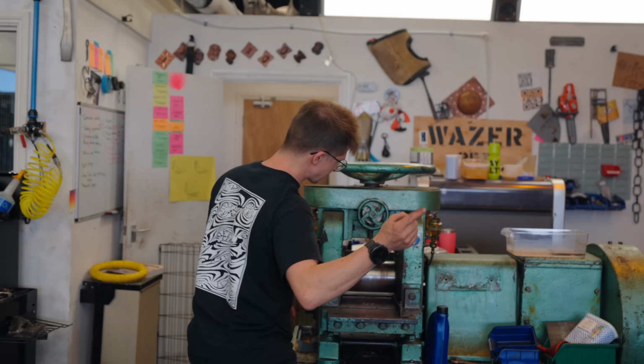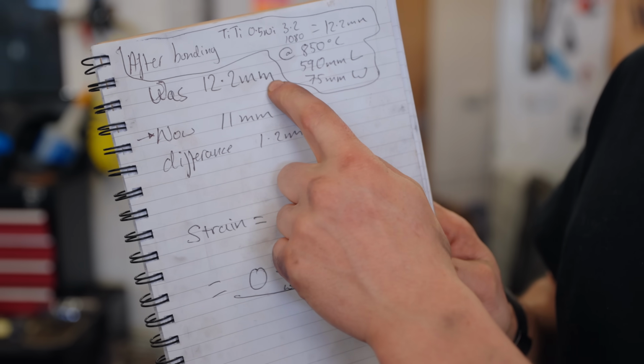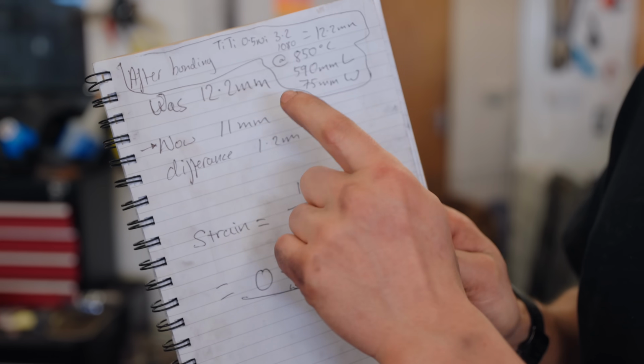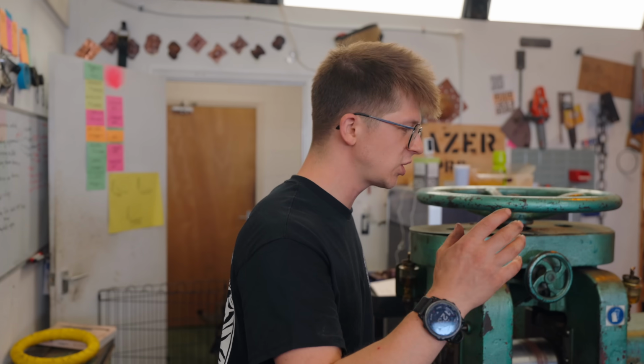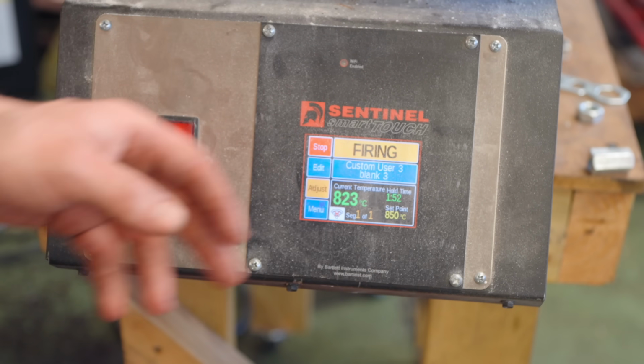3rd sample, I'm going to take to the rolling mill. Remember, it was 12.2 millimeters. We bonded it. It then became 11 millimeters. My plan is to apply approximately 0.1 strain with each heat and see if, at a lower temperature of 850 Celsius and with pretty low strain per pass, it is forgeable now.